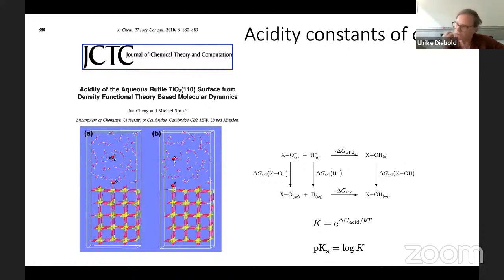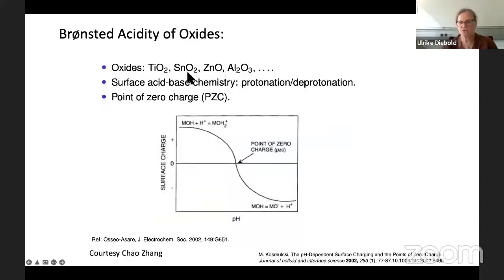There's really no way to compare these calculations to any experiment. The only thing one has is the point of zero charge, right? So you can go, for example, to this nice compendium of point of zero charge. The way it's measured is just by putting these materials in solution and changing the acidity, the pH, of the electrolyte, and then the point of zero charge is when the surface is uncharged. So that's what you can get, but that's really an overall property. Sometimes people do it for different facets, but it can be very different for different atoms, right? So that's the question that we had.